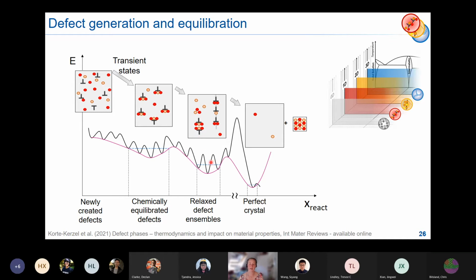And then at the end of the day, you'll of course not have defects in a kind of long-term thermodynamic consideration. You would have some point defects and two separate crystal structures, right? But the important thing is that we have this in our alloys, and our actual design target is somewhere here. We hardly ever go to actual equilibrium in what we use in everyday life. So what we want, and that's important, is that we have local minima here that we can stay in for a long enough time.